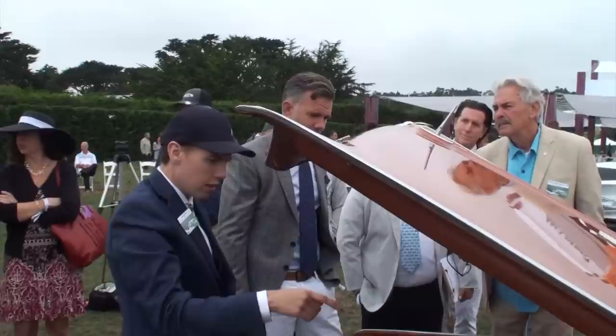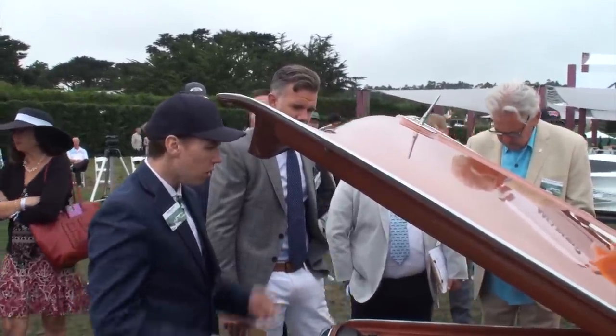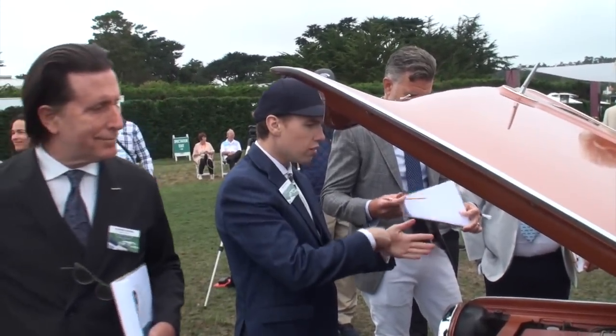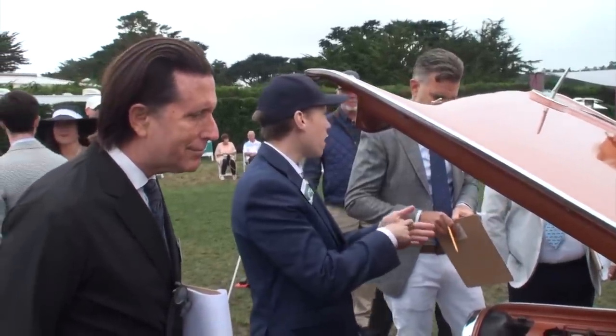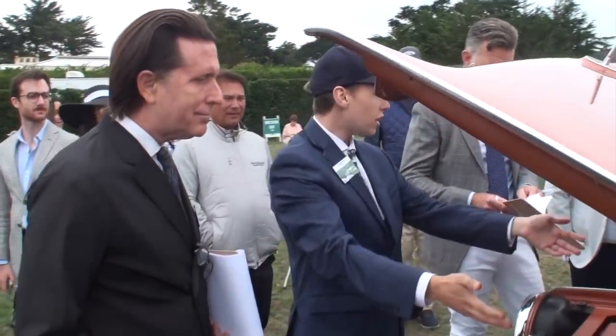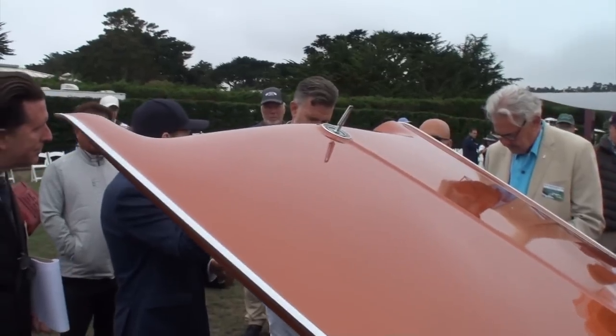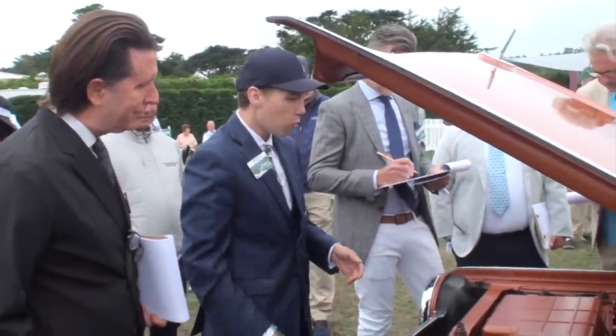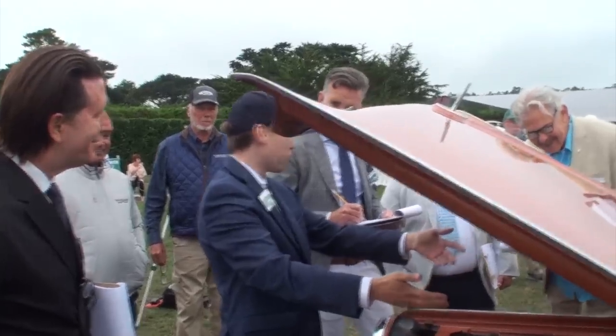They're proud of that. And then there were a lot of problems that occurred over time. Up to car number 19, the compressor blades on the turbine shaft were friction welded. Around 25,000 miles, that turbine blade would let go and explode inside the engine. One of the first ones happened to Bill Carey, the guy he called if he had any problems before. And he's like, wow, well, there's no holes. Well, our construction works. At least that part's safe for the public.